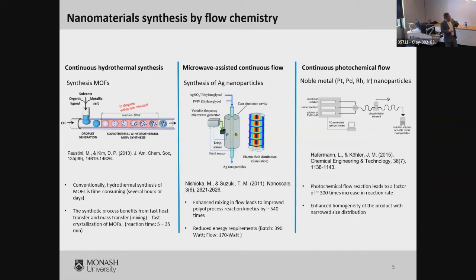The other example I have here is a photochemical synthesis where they have prepared platinum, palladium, etc. nanoparticles, and you can see a 300 times increase in reaction rates. And also the advantage is that it gives a narrow distribution of particles, which are quite exciting in terms of applications.